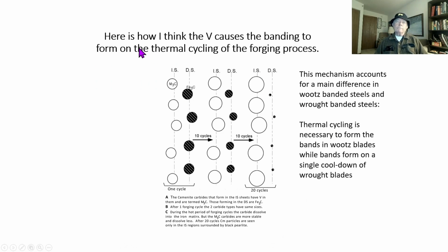Now here is an explanation of what I think is going on. I've shown here the distribution of the 2 types of carbide after 1 thermal cycle. So after 1 thermal cycle, because of the dendritic solidification, you'd have M3C over here, and over here you would just have plain old Fe3C, because that's pure iron freezing over there in the dendrite regions. Okay, so we heat that baby up, and what happens is that these guys, not having vanadium in them, will dissolve into the austenite much faster. So after a few cycles, this gets bigger and that gets smaller. After a whole mess of cycles, you see these guys lined up and pretty much nothing left over here.